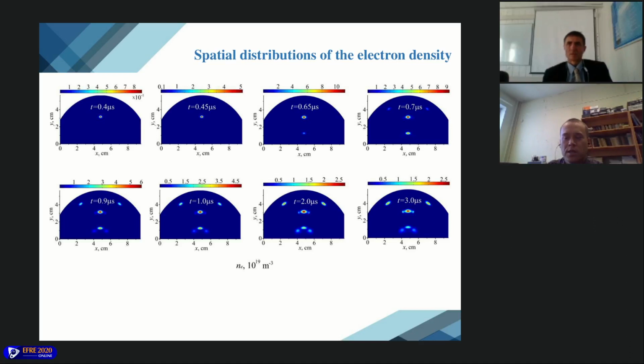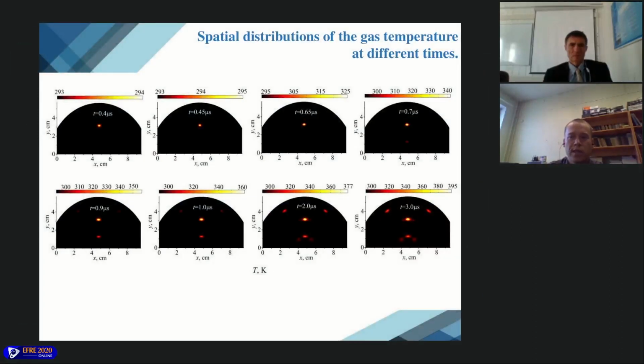The first is at the main focus of the system; the second, the lower one, is located near the microwave radiation source, which is a structure of 3 grouped plasma formations; as well as 2 upper plasmoids symmetrically located near the surface of the parabolic mirror. Next slide. This slide shows the dynamics of the spatial distribution of gas temperature.